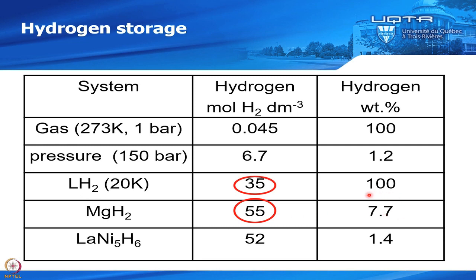But the disadvantage, as you see here, is that the gravimetric density is quite low. So here, this means that you only have 7.7 weight percent of hydrogen in a metal hydride tank made of magnesium hydride. Okay. And the rest is just the weight of magnesium. And for lanthanum nickel 5, it's even worse. It's only 1.4 weight percent. So that's one of the big disadvantages of metal hydride.